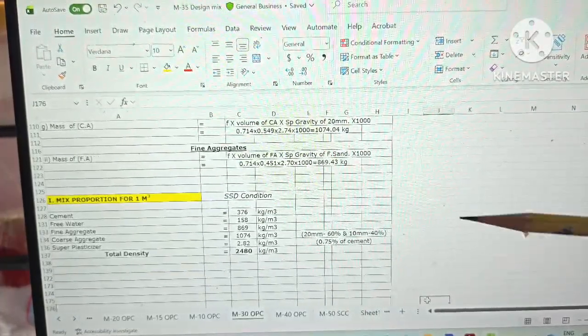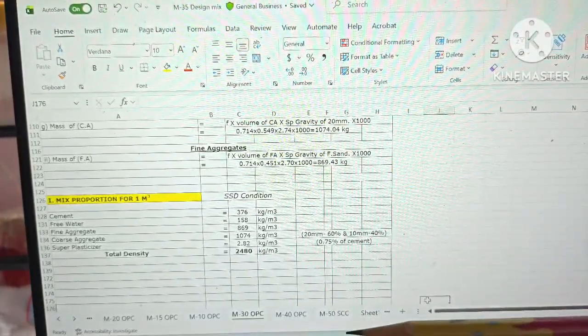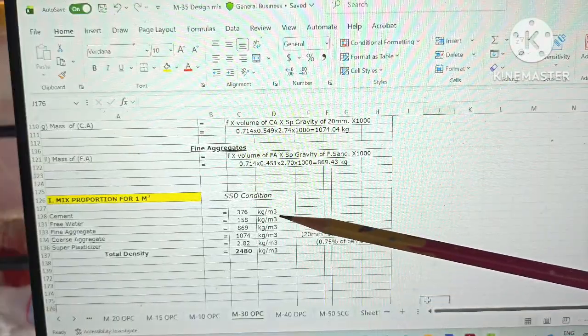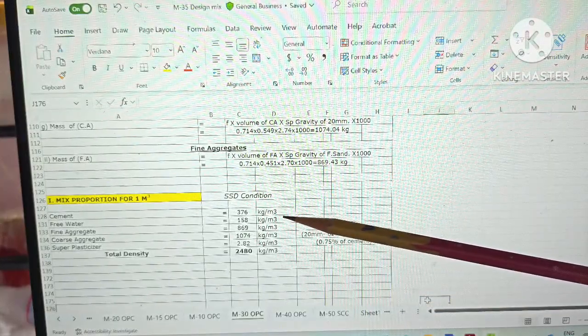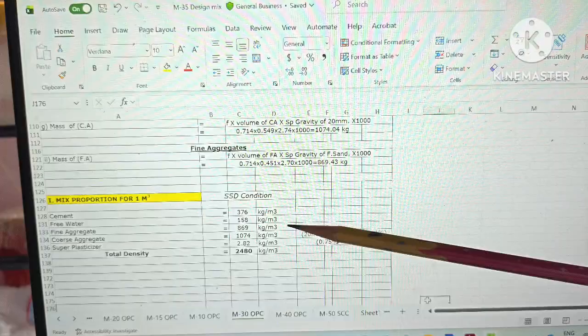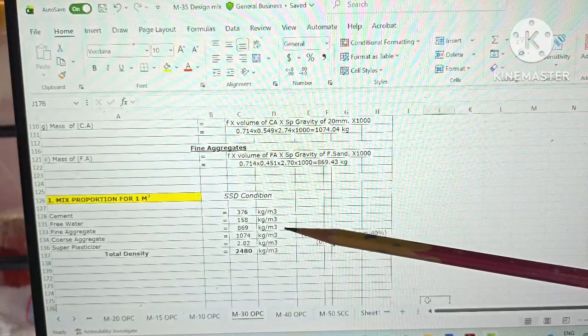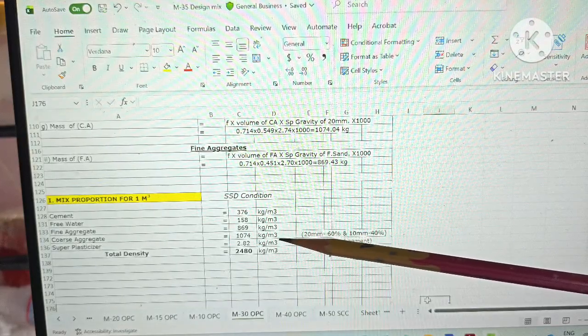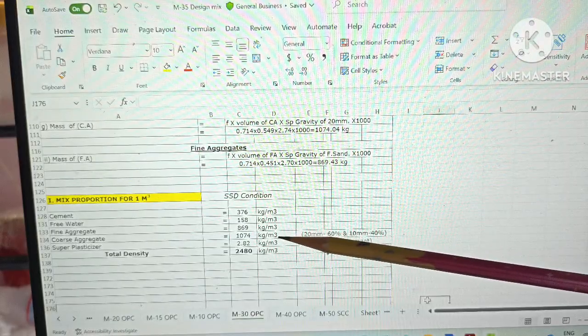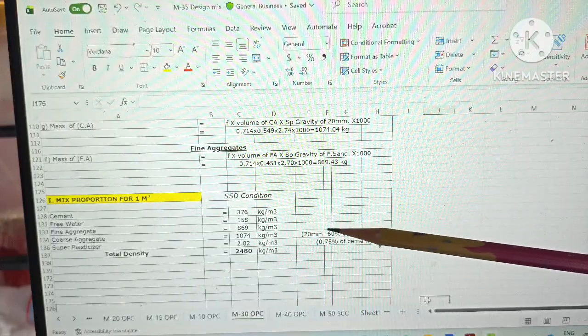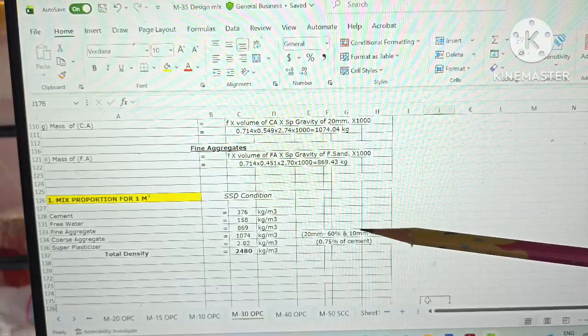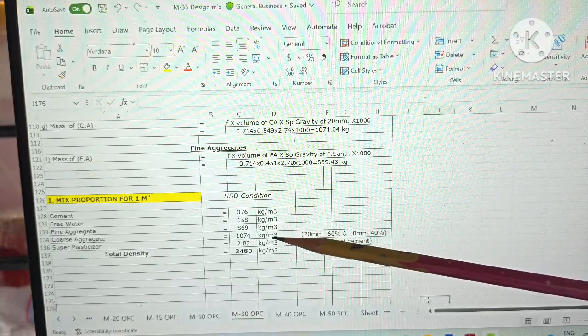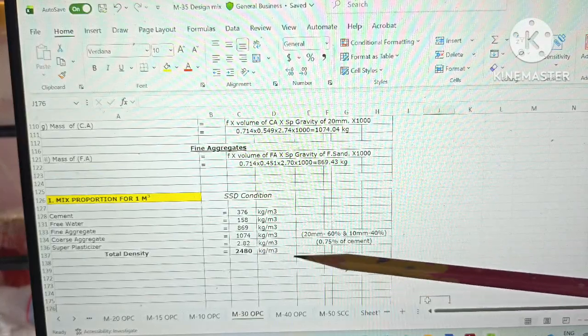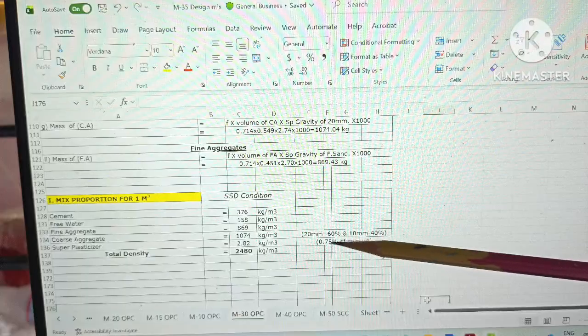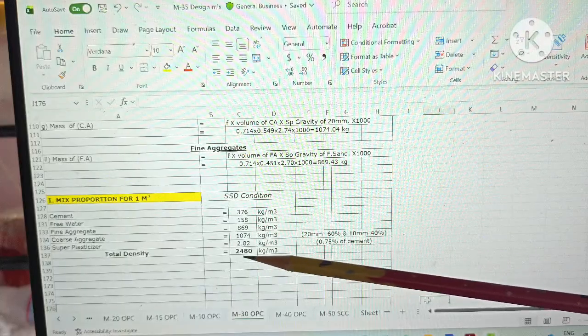Now the final proportion derived by doing all this calculation for 1 m cube is: cement is 376 kg per meter cube, free water is 158 kg per meter cube, fine aggregate is 869 kg per meter cube, coarse aggregate is 1074 kg per meter cube. Now this coarse aggregate can be further divided into two, that is 20 mm we can take 60% and 10 mm we can take 40%, and lastly the super plasticizer is 2.82 kg, that is 0.75% of the cement. Our final density comes to 2480.